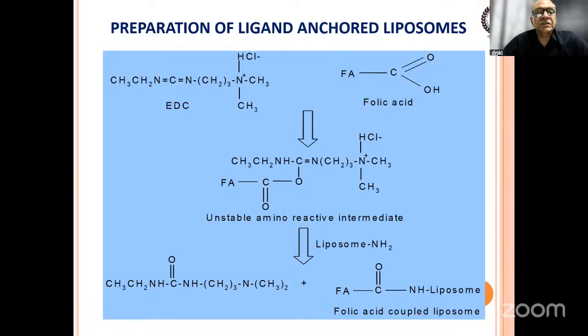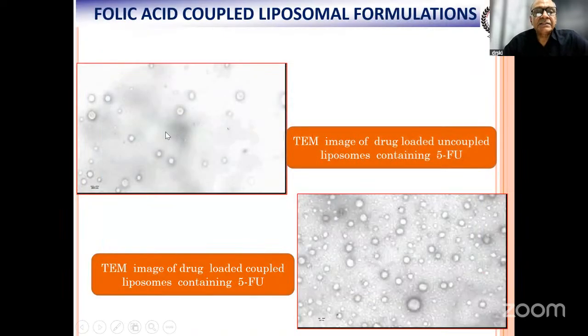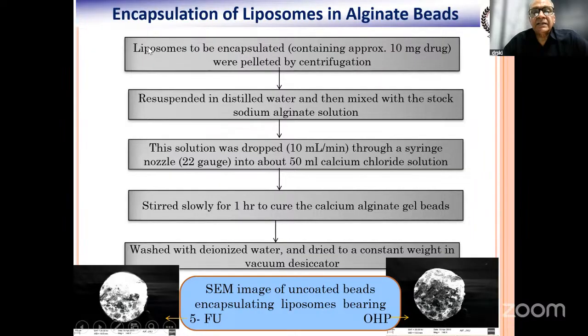A number of nanocarriers can be used for the preparation of such a drug delivery system. Here the liposomes are liganded with folic acid using carbodiimide chemistry. This is a transmission electron microscopy photograph of the folic acid coupled liposomes containing 5-fluorouracil. This is the uncoupled liposome, and this is the coupled liposome, meaning folic acid was coupled on the surface of the liposome. Then the liposomes are encapsulated in alginate beads.